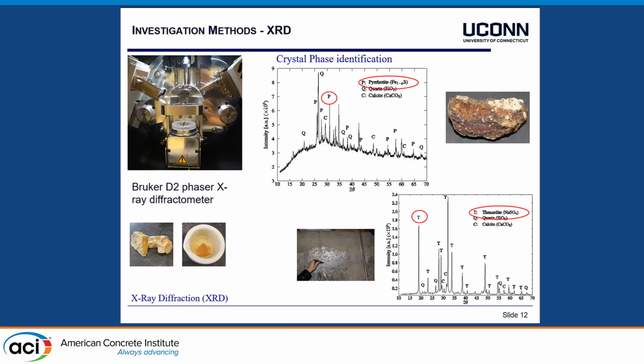Using XRD as a qualitative measure, you can use some aggregates. For example, we used aggregate from the Becker's quarry which was already oxidized, and we scraped off those oxidation products just because it's high in intensity, pulverized this, and then, if you use the JADE software to look at the pattern of those intensity peaks, you can identify that actually pyrrhotite is present there. Or with those whitish discolorations or deposits near the cracks or at the walls, if you're using XRD, you can determine that there's, for example, a sodium sulfate present.